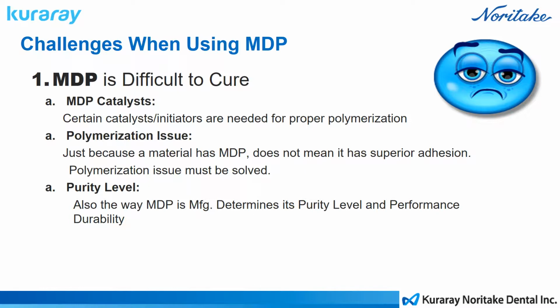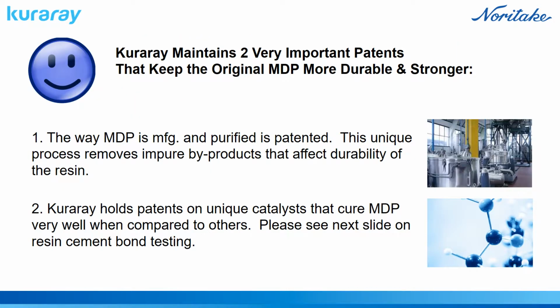Challenges with MDP. Usually with almost anything, you have these great features, but there's always a challenge you have to overcome. Well, the MDP is a little bit difficult to polymerize, and that is what gives you the strength of your chemical bonding. It has a great affinity to dentin, but then it needs to polymerize to create a strong chemical bond and for it to last. Also, you have to have these catalysts that work with it, that overcome this weaker polymerization, and then the purity level. You have to manufacture the MDP and get rid of some impurities, and Kuraray has a special manufacturing process for this as well. So we actually have a patent on the way MDP is purified and processed that people cannot infringe upon. And we also have a patent on catalysts that work with MDP that give it its high level of polymerization and also compatibility with other materials if you decide to use another self or dual cure product. And we've seen studies on this in the past 3 or 4 years that are very dramatic.